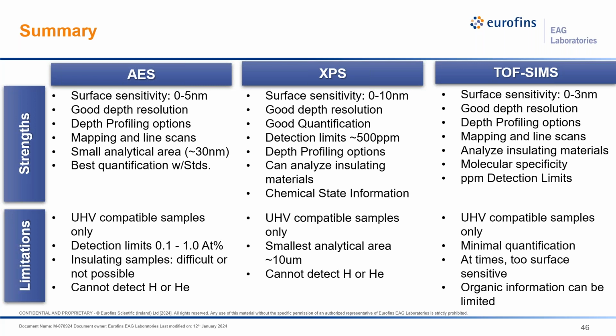Limitations also, hydrogen and helium are not detected, as I mentioned, in Auger and XPS. And then for time-of-flight SIMS, the limitation is that the quantification is limited. Sometimes it's too surface sensitive. A tiny bit of contamination created during sample prep or packaging can cover everything that we're actually looking to see. And sometimes the organic information can be limited. Samples that have been through a heating process or something of that sort, where the organic information is now lost.